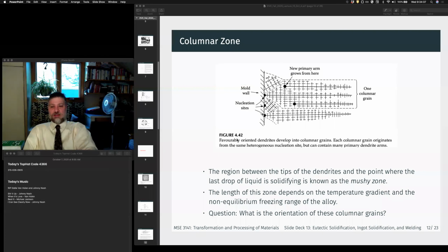so that you're selecting for a particular orientation. Only certain crystals can survive. It's a step above directionally solidified, because the directionally solidified grains are columnar, but it's still a polycrystal. The pigtail for casting was developed by a group of different people. And no, you don't actually need a seed crystal for superalloys.